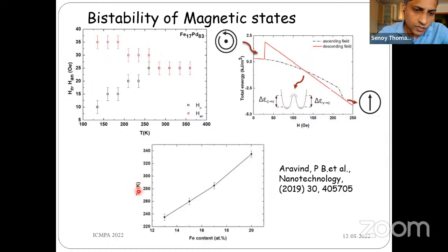So we extracted the bistable temperature for iron palladium alloys having different compositions, and what we found is that the bistability temperature T is increasing as you keep increasing the iron content in the alloy. This is basically due to the fact that as you increase the iron content in the alloy, you are increasing the exchange energy, and thereby you are also increasing the energy barrier. So we have to supply more thermal energy to overcome this energy barrier. That's why T is increasing as the iron content in the iron palladium alloy is increasing.